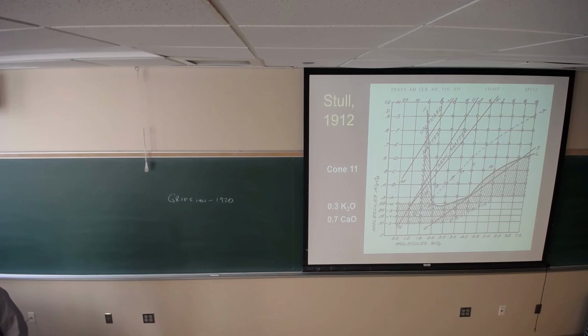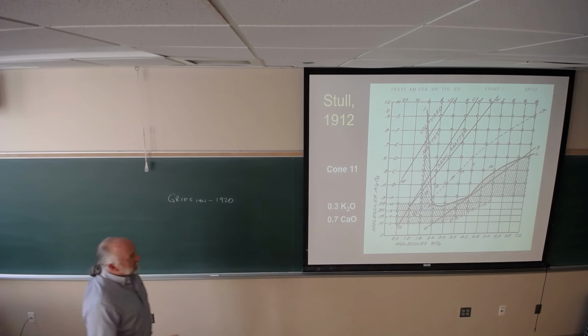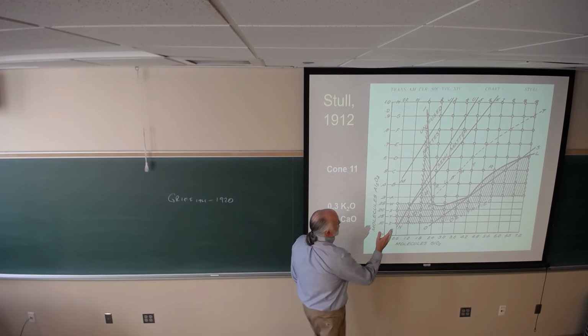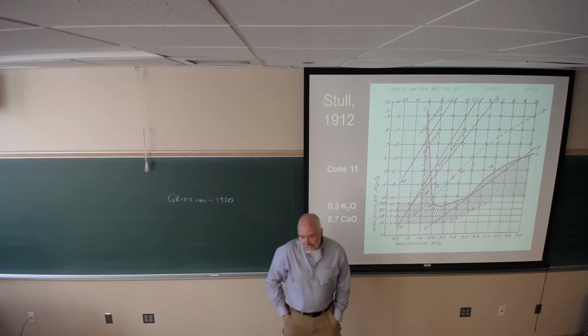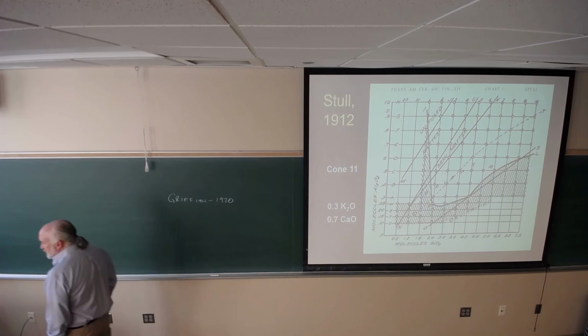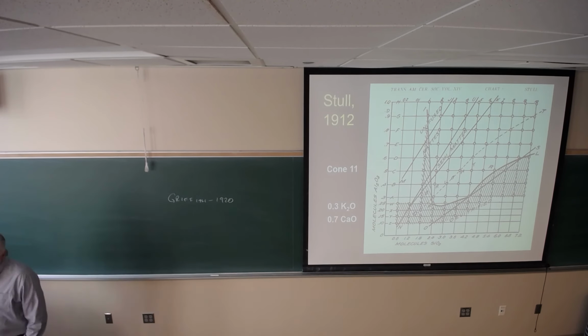And what he found was something even more interesting. He found boundaries for behavior. These are matte glazes here. These are bright or gloss glazes. And these, he says, are devitrified, which is actually incorrect. Devitrified then indicates that they were vitreous, and then they crystallized on cooling. Okay? And that's not true.